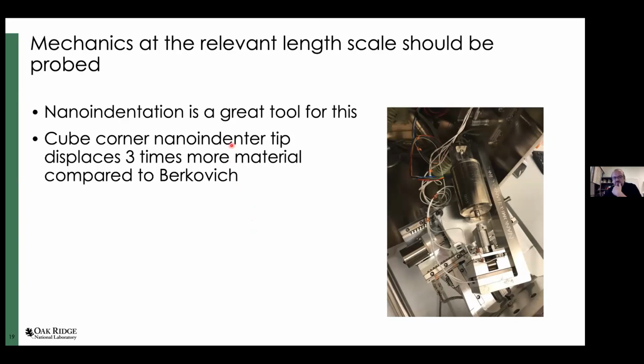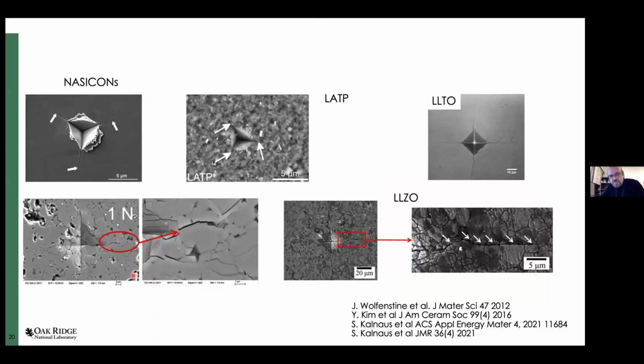And to probe the fracture toughness at the nanoscale, we typically use the cube corner nanoindenter tip, which displaces 3 times more material compared to the Berkovich nanoindenter tip. So you really create very high stress inside the material to reduce the threshold load for fracture. And here is the illustration of the problem that we're dealing with. These are some from our experiments, some from the literature. What happens in the majority of the crystalline solid electrolytes that are out there, these are the residual hardness impressions done by the cube corner nanoindenter, and you can clearly see these cracks propagating from the nanoindentation.